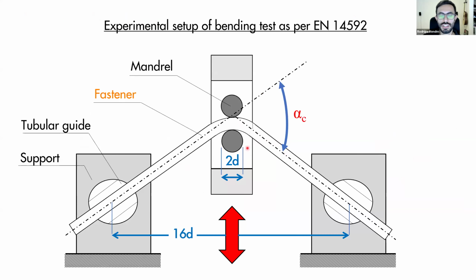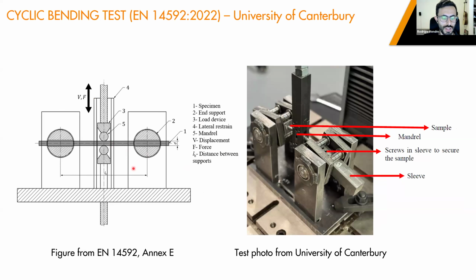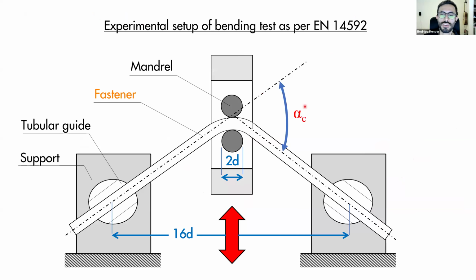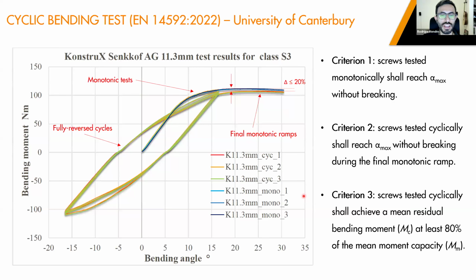The bending moment and also the bending angle are measured. This is the bending angle, just for you to know. It must be shown in the standard, but you can see here a sketch I made. And this is basically the graph that you get from the test. Here you can see the monotonic test, three curves that are monotonic. You can see they are a little bit stiffer than the cyclic tests. And here the cyclic tests, also three. You can see three fully reversed cycles, and then the final monotonic ramp, as you can see here.